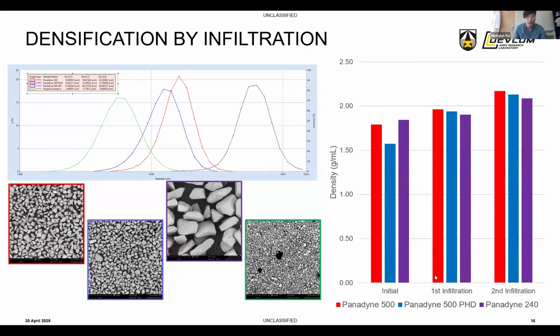And this shows that here, right? In the red, blue, and purple, we looked at 3 different silicon carbide feedstocks. We printed parts, and then we did 2 cycles of infiltration and pyrolysis. What you can see is the particle size distribution of the feedstock affects the print, but it also affects the density of the print. And because you're getting different pore sizes, it also affects how it infiltrates and how it pyrolyzes, right? So this is definitely an area of interest for us, not only in terms of the chemistry of the pre-ceramic polymer that we're infiltrating with, but also viscosity, because that affects how it infiltrates, and then also the particle size distribution and printability of the powder itself.